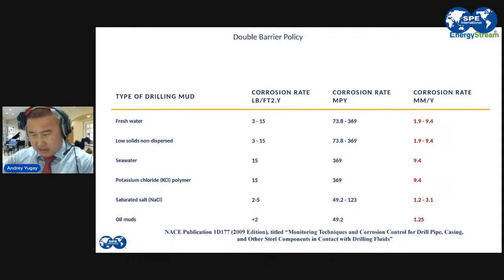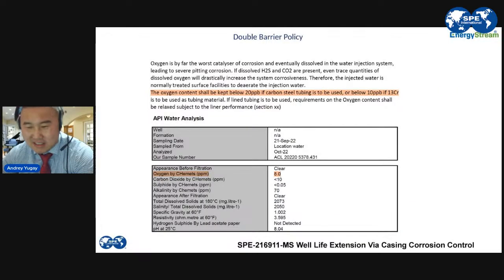NACE recognized that there is a very high corrosion rate of drilling equipment and well equipment. Sometimes it's reaching, as you can see here, 9 millimeters per year. 9 millimeters. What is the thickness of our casings? It is around 9 millimeters. So imagine the corrosive rates could be so high that we can lose our casing in 1 year. Now, why I'm talking about the Pepsi Cola, what it has to do? You know what is dissolved oxygen? Same like dissolved CO2 in the Fanta or Cola or Sprite.